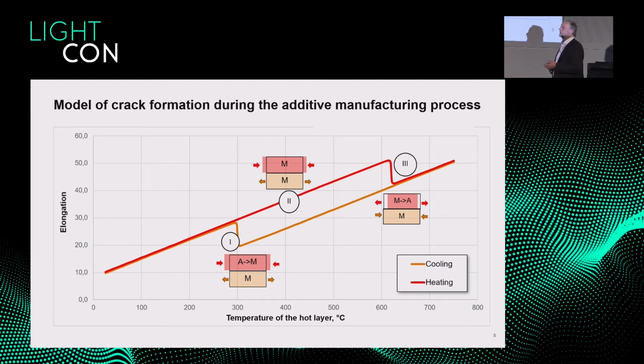Actually, we use an austenite grade, 316L. It's a pure austenite even at low temperature, and it has a low carbon content, so it has a good weldability. So this works for the case 1. It's a very good steel.